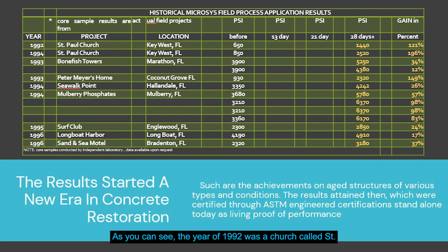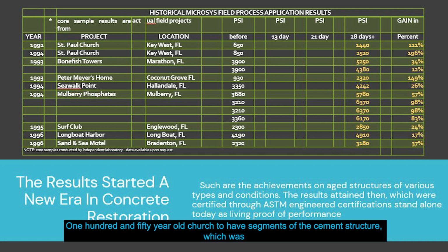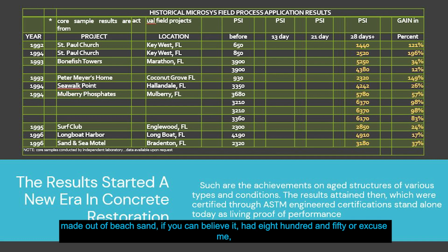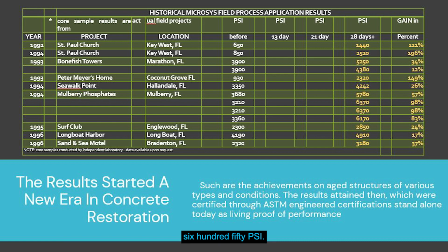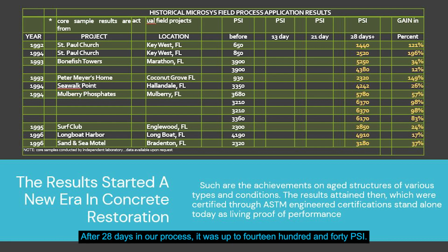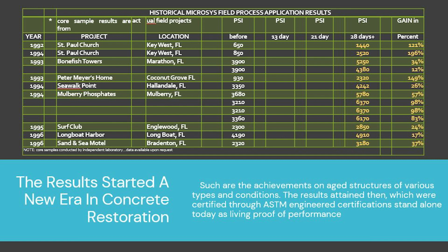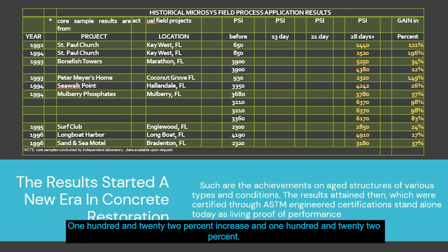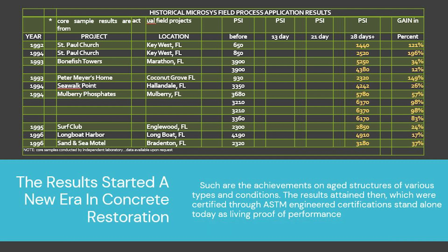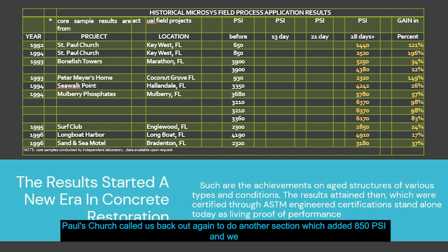As you can see, the year of 1992 was a church called St. Paul's Church down in Key West, Florida, a 150-year-old church that had segments of the cement structure, which was made out of beach sand, if you can believe it. It had 650 PSI. After 28 days in our process, it was up to 1,440 PSI, a 121% increase in PSI, 121%.